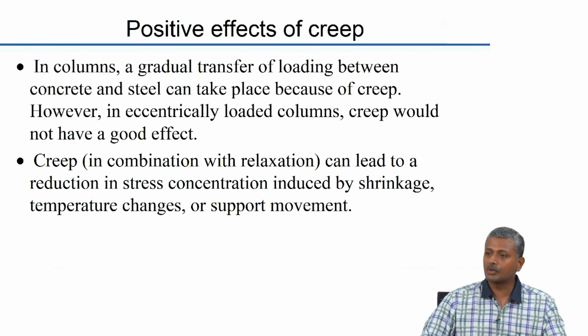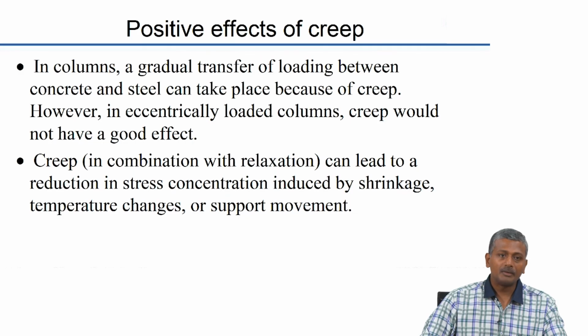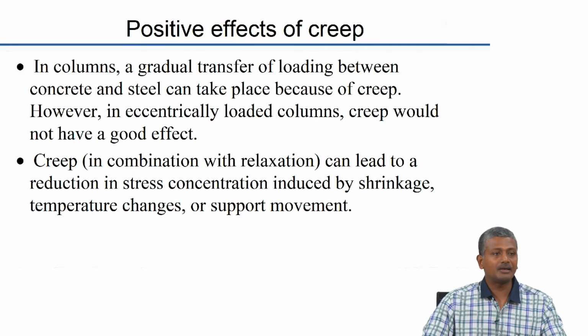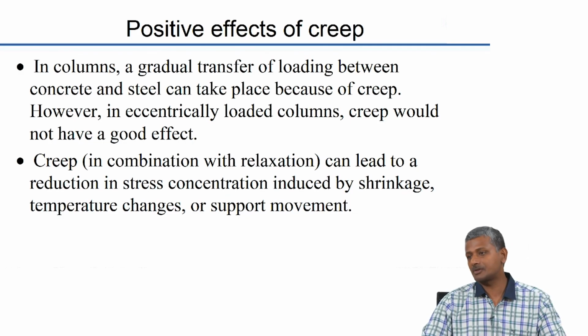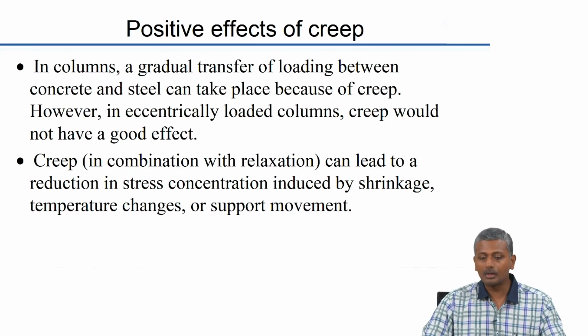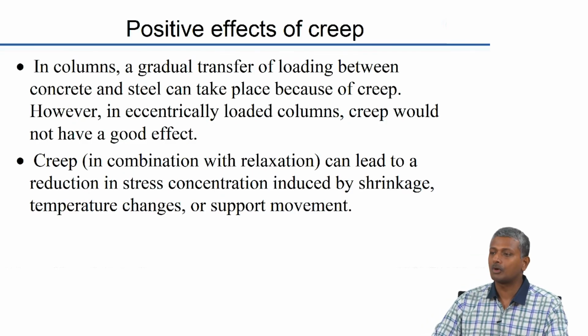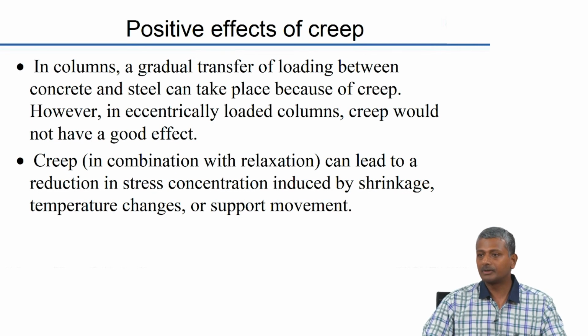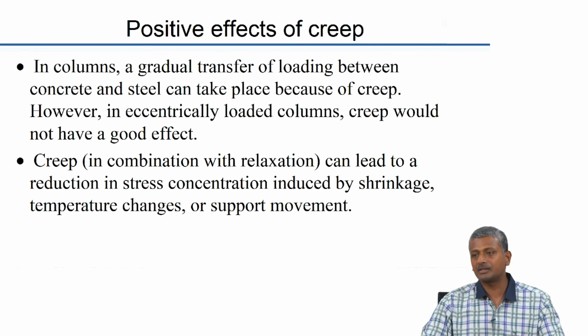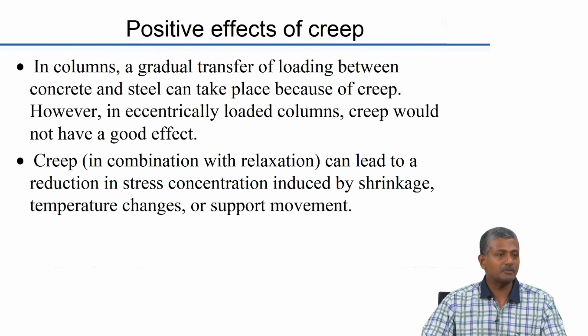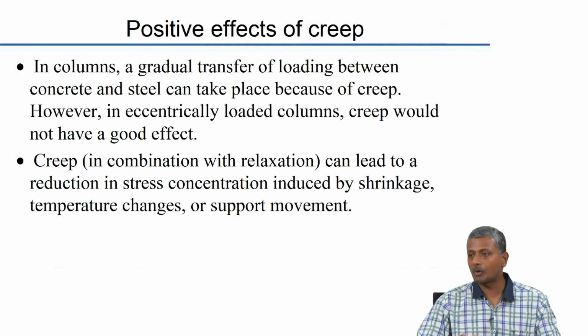Now, in some cases you can also get positive effects of creep, because internal rearrangement can lead to reduction of stress concentrations, and in columns you can have a gradual transfer of loading between concrete and steel because of creep. Because there is deformation happening in the material, the stress transfer can happen much slower, and overall in eccentrically loaded columns you will have a problem though.